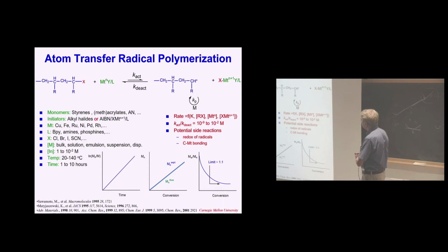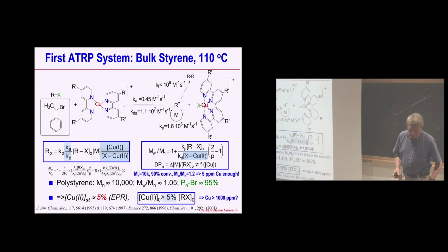And rate would depend on this equilibrium constant, or ratio of these two rate coefficients, on concentration of alkyl halide, transition metal complexes. And these activation, deactivation processes depend very strongly on the nature of monomer, sometimes also on reaction conditions, which means temperature and solvent, and also they will depend on the particular catalytic system. So how do these reactions occur? I will show you later what happens in the sense of chemistry and transition state, but typically it goes via inner sphere electron transfer process.